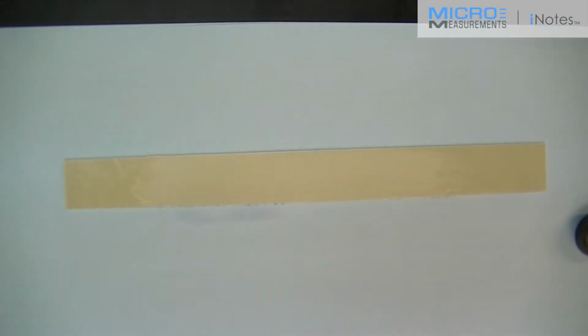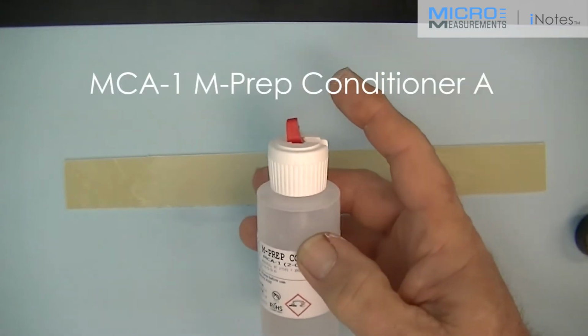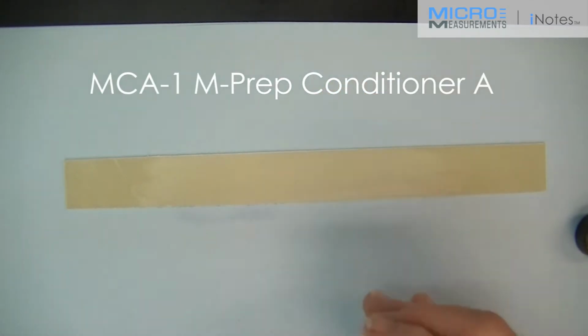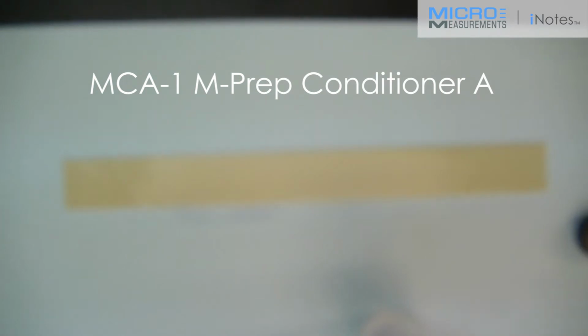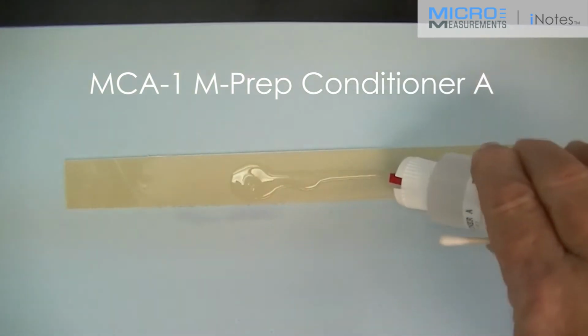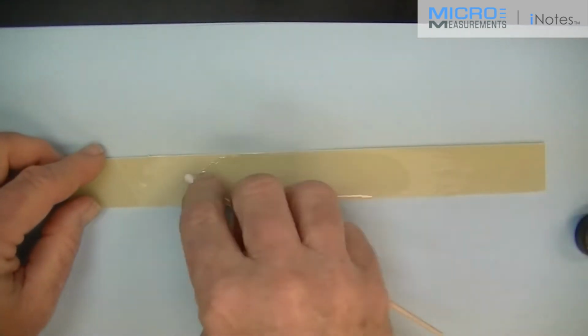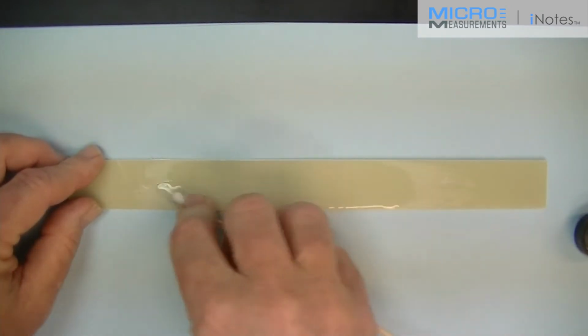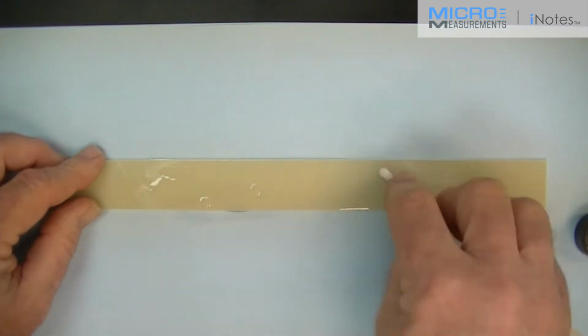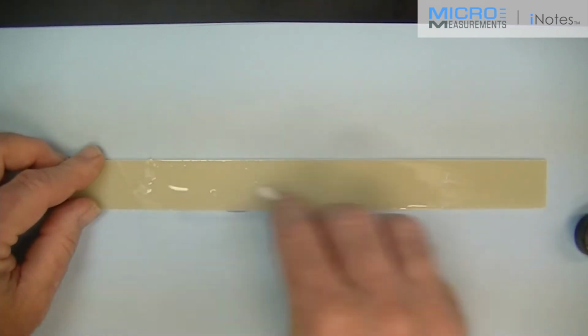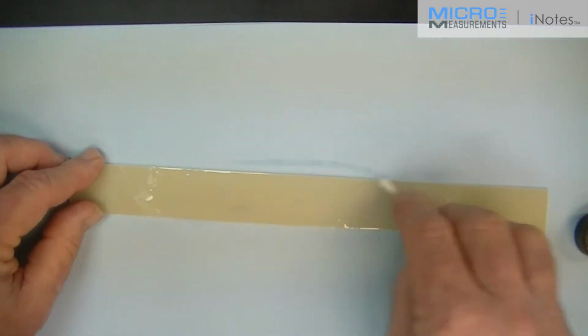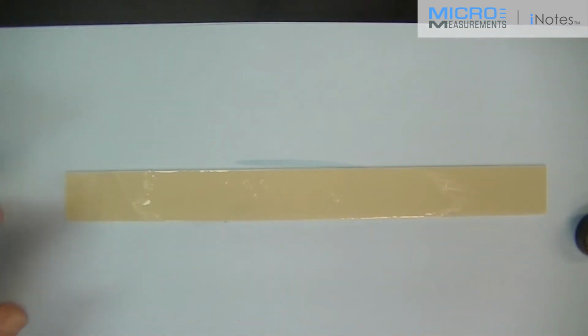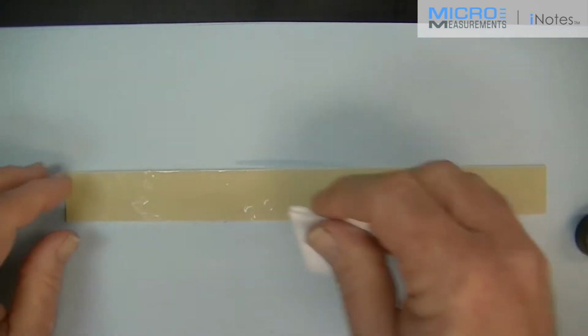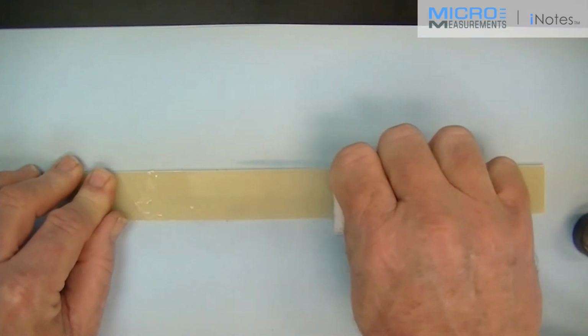The next step will be to locate the Conditioner A, the mild phosphoric acid solution, red tip bottle, and a cotton tip applicator. I'm going to flood the surface of the beam with the Conditioner A. This is going to remove any organic contaminants left behind and also put the dust or debris that was sanded into suspension so that we can blot it away. Take a clean, dry gauze sponge, fold it into quarters, and with a single wiping motion, absorb the material off the beam.